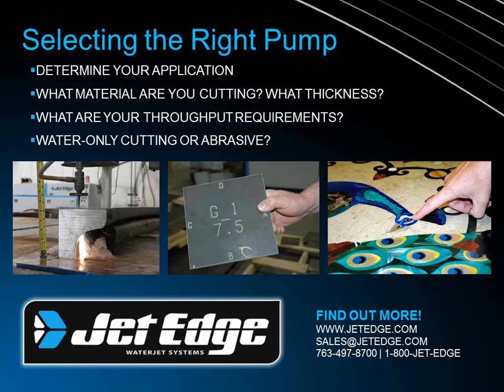Substantial increase in speed. In doing so, I'm utilizing more garnet. But typically when we analyze it and look at just the consumable cost to operate that nozzle, the increased speed will actually result in a somewhat lower cost per inch of cut. Now the newest technology that we've introduced, the extreme pump with the 90,000 psi, allows us to increase our operating pressure from 60,000 continuous pounds of pressure to a 90,000 pound deadhead pressure, or 75,000 continuous pounds of pressure.